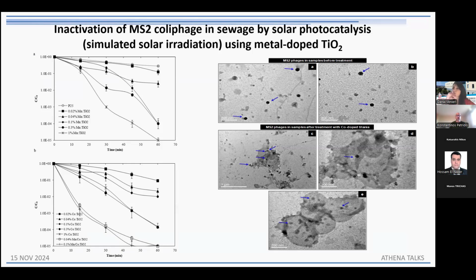It is not a mild procedure, like, let's say, disinfection of potable water. Here we deal with organics, nutrients, inorganics, interfering substances, which actually inhibit the overall process of disinfection. However, at least under simulated solar light, we can see here that those viruses were quite reduced during treatment. However, I should point out that prolonged treatment periods were required. I mean, 60 minutes for disinfection is quite a long period.